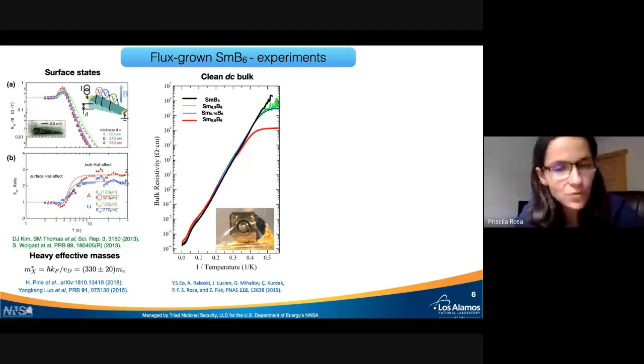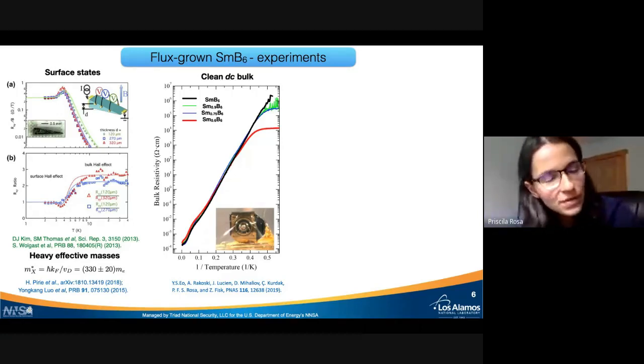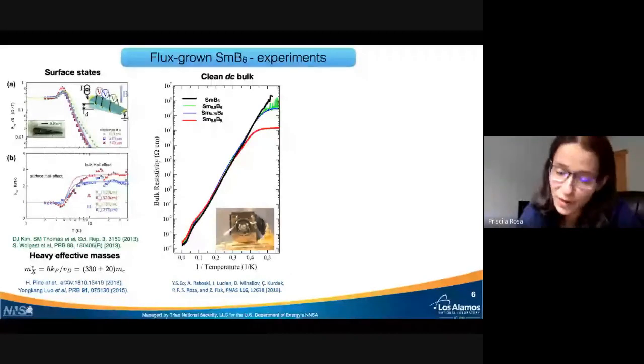So these measurements were really able to show that the DC bulk of samarium B6 is clean, and combined with the surface state measurements, they really show that the bulk is an insulator and the surface states are heavy. However, there's one more piece of information there.